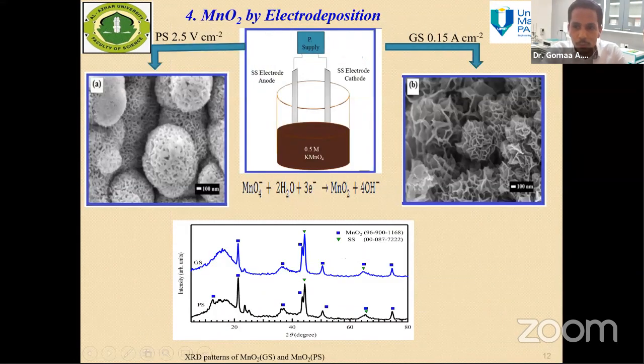So in these 3 examples, we successfully prepared manganese oxide from a waste source, spent zinc carbon battery. On the other hand, we also compared with chemically produced manganese oxide. So we used the same electrodeposition technique to deposit manganese oxide from a chemical source, potassium permanganate. And we applied 2 techniques. One is applying fixed current, and one applying fixed potential.